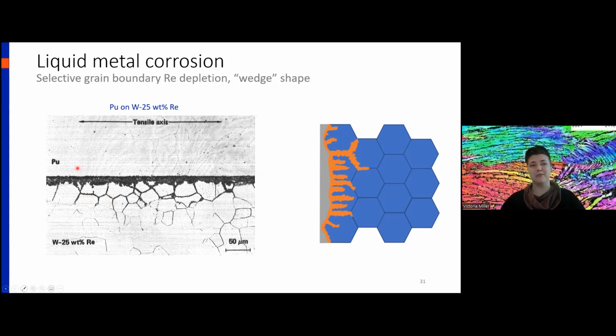This is my favorite example because this example is molten plutonium on a tungsten rhenium alloy. And you can see you get a surface film of corrosion, and you get selective grain boundary rhenium depletion. And if you look at the grain boundaries, they have this characteristic wedge shape because depletion is more severe near the surface than it is toward the interior of the material.